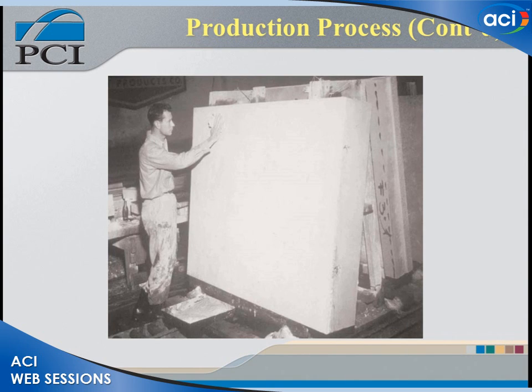The panels were initially cured for 3 days, being thoroughly sprayed with water at least twice a day. On the 3rd day, a solution of 1 part of hydrochloric acid to 5 parts of water was applied and then brushed off using plenty of water. The proper degree of acid etching for uniform texture was then checked under a very strong light.